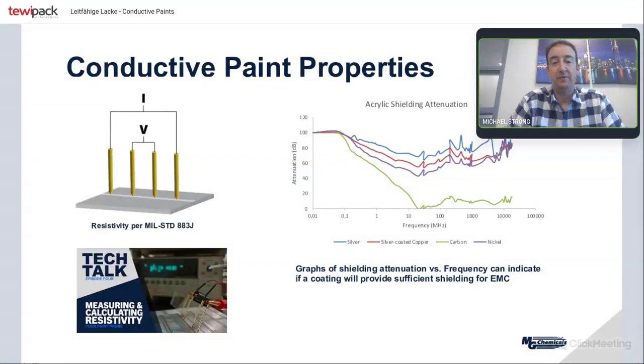And then as we stack them, and this is our acrylic series line, we can see that it lines up with what we had said in the prior slide. Carbon, again, really a big drop off once you hit 10 megahertz. So really above 5, you're not that effective. Around 5, you're still around 40 decibels attenuation. So it does work quite well, but beyond that, you see it drop off and really not be all that effective. The purple curve is nickel, followed by the red curve, silver-coated copper, and then finally silver.